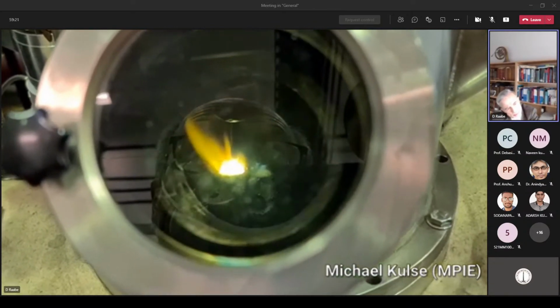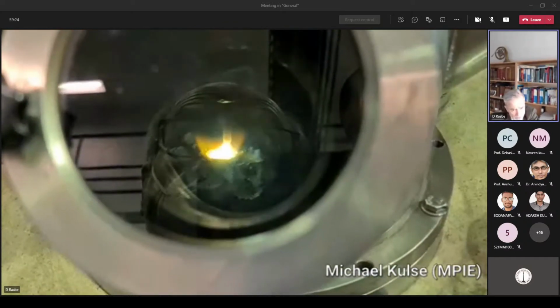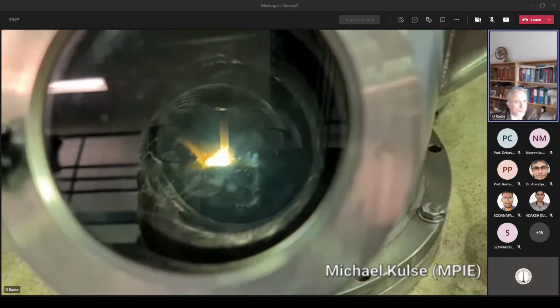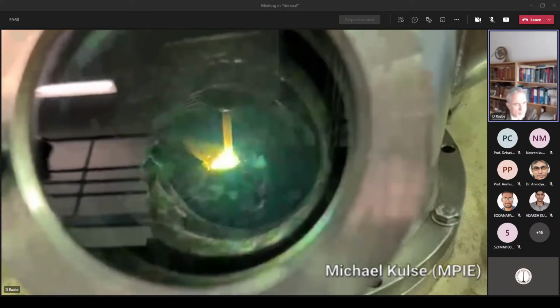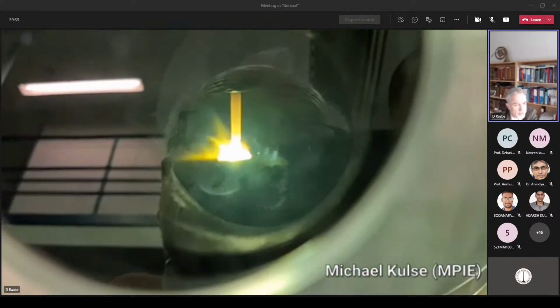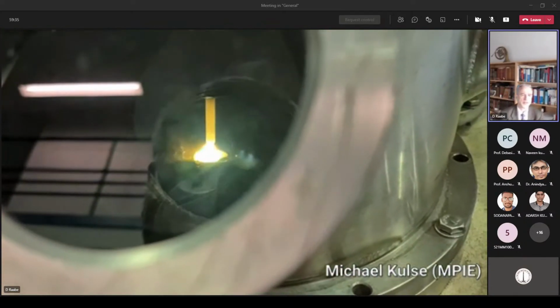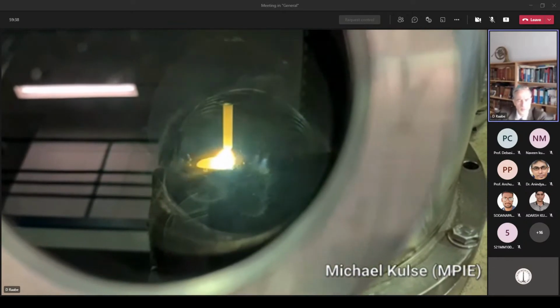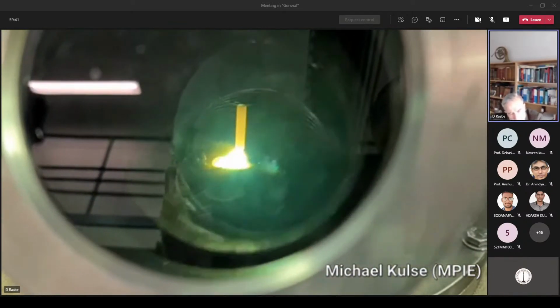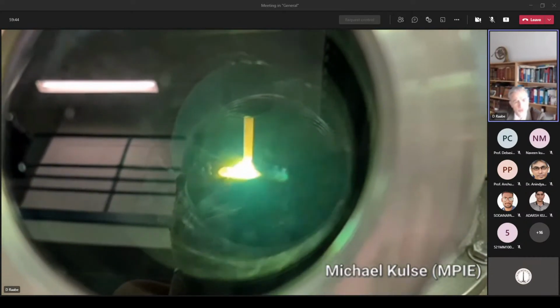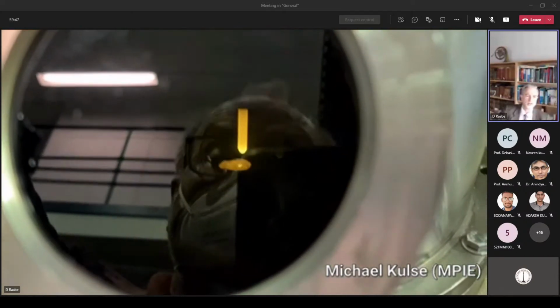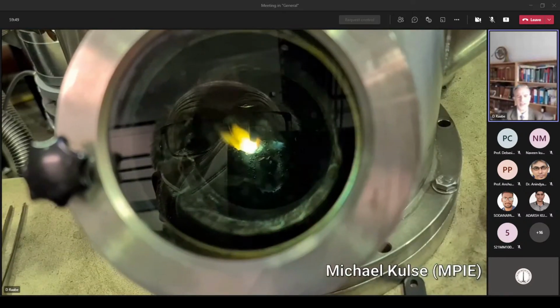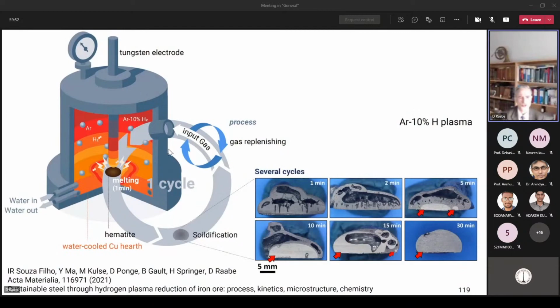And here we have such an experiment in one of our plasma furnaces that is now flooded with a mixture of argon and hydrogen, where we play, of course, with different partial pressures of hydrogen. And we are currently also working to understand details of the plasma a bit better. But you can here nicely see that, depending on the gas and on the plasma state, you have different types of interaction between your arc and the type of oxide you melt. But at the end of the day, you arrive, as shown in this overview diagram, with this simple experiment, in this case with only 10% hydrogen, at a very efficient reduction method.